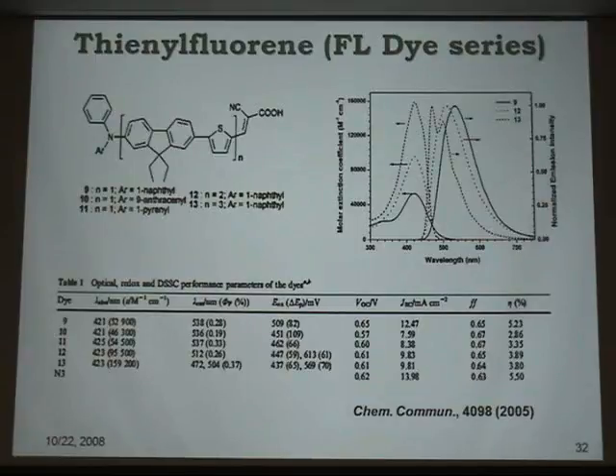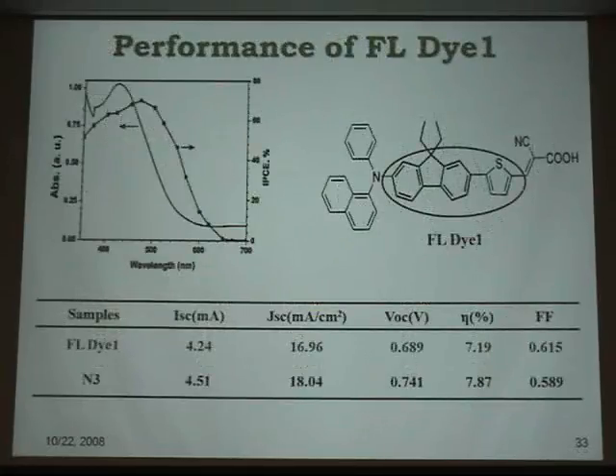And the efficiency achieved with this dye, FL dye, is about 90% of N3, 5.23 compared to 5.5. Now, if we make it thicker, it will help. And the efficiency achieved by this dye is about 7.19, and N3 is 7.87, the same dye. And again, 90% of efficiency is preserved compared to N3.